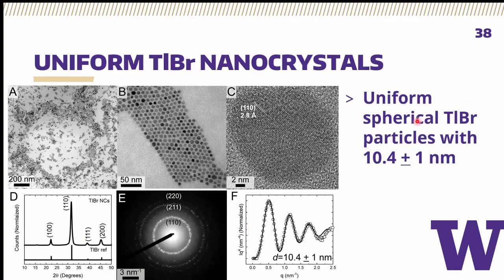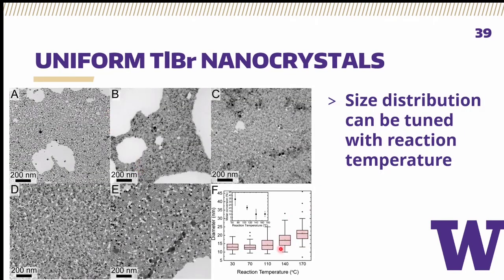Doing this with thallium bromide, we were able to make these super uniform spherical thallium bromide particles with very uniform sizes, smaller than anyone's been able to make before. These materials could potentially be used in radiation detection applications. They already are. And so this is very exciting, to get these nice uniform nanocrystals. We're able to show that we could tune the size distribution of these nanocrystals over a limited temperature range by just increasing reaction temperature from 30 to 170 degrees C.